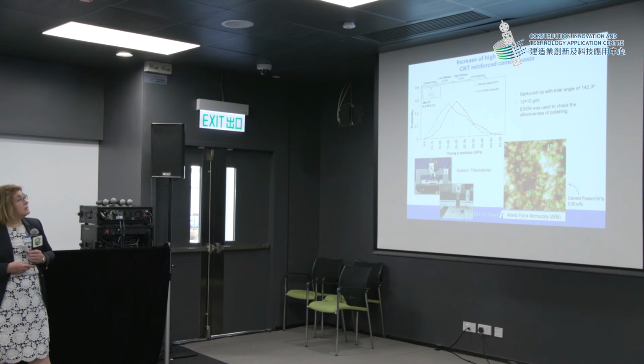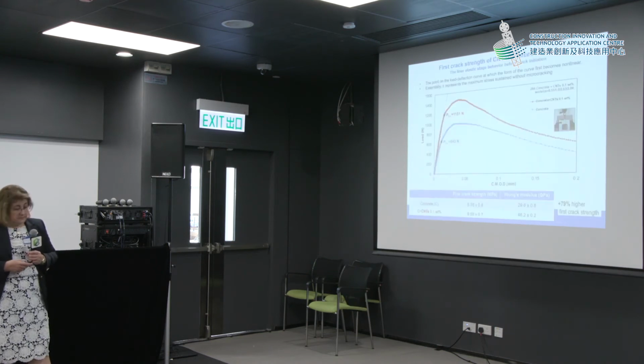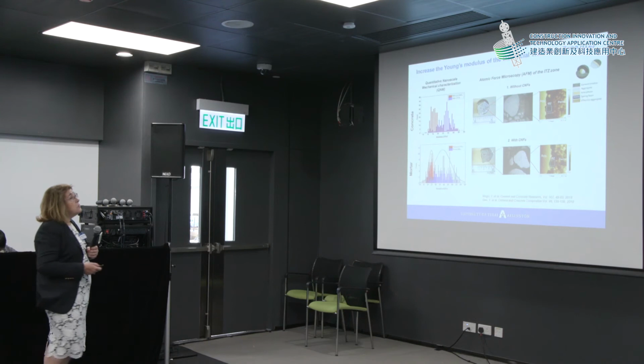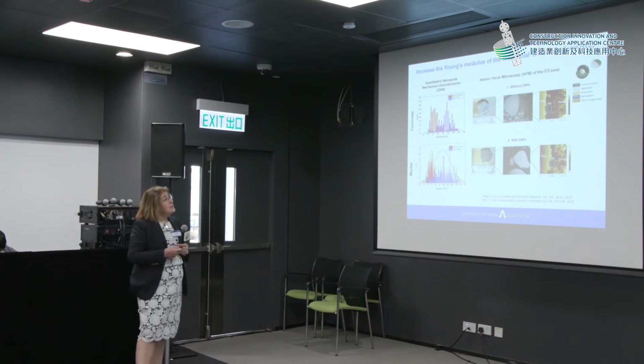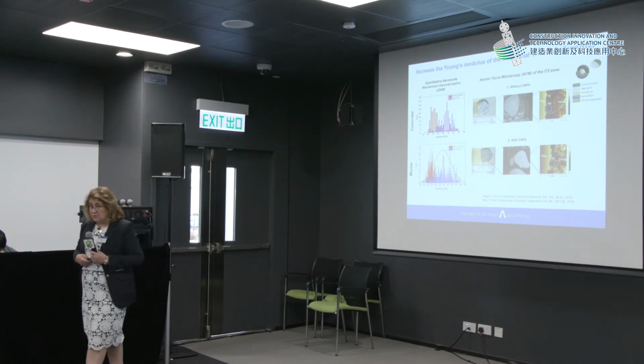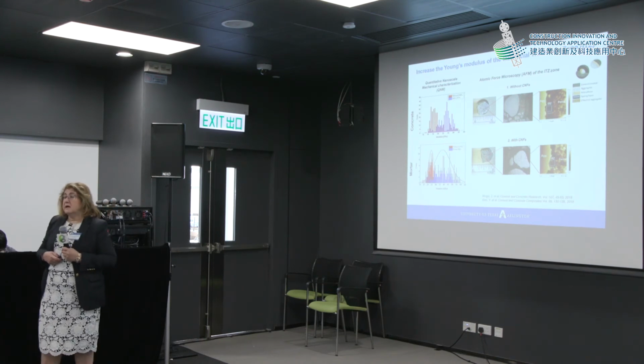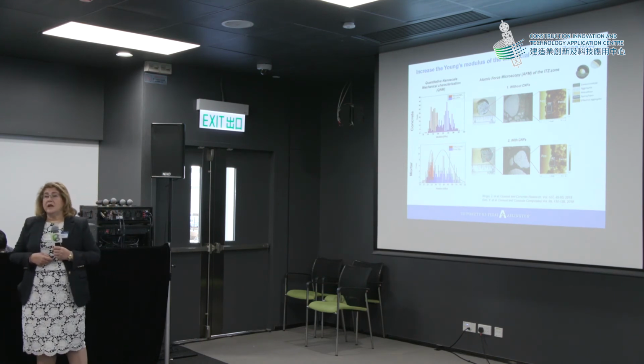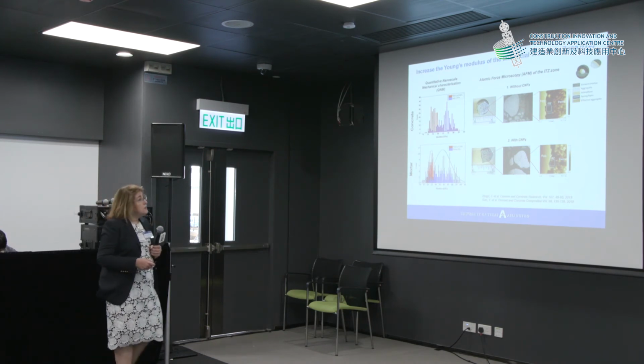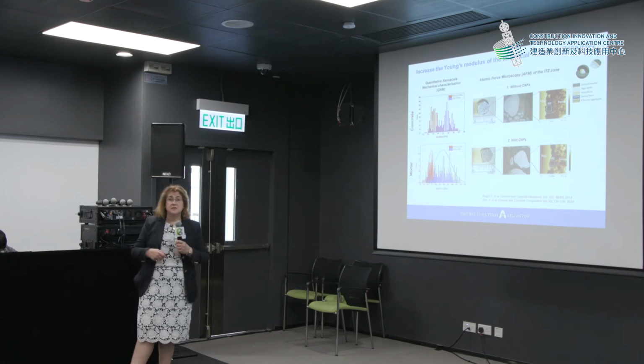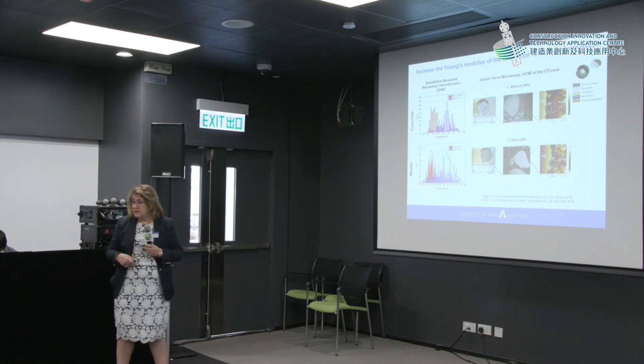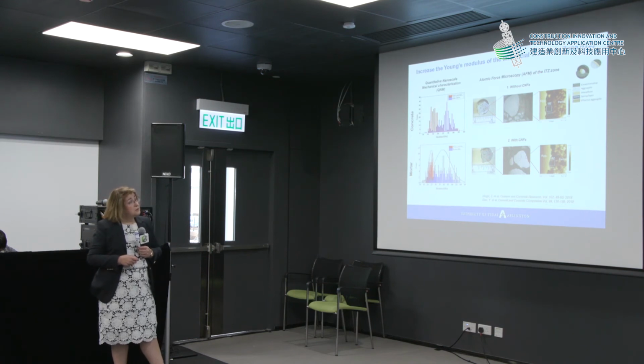in our early research. Later, we were able to identify that the Young's modulus was highly increased at the interfacial transition zone, in a similar way to what we have observed so far with silica fume. And silica fume is giving us adverse effects like high shrinkage cracking. Carbon nanotubes do not give us any of those adverse effects.